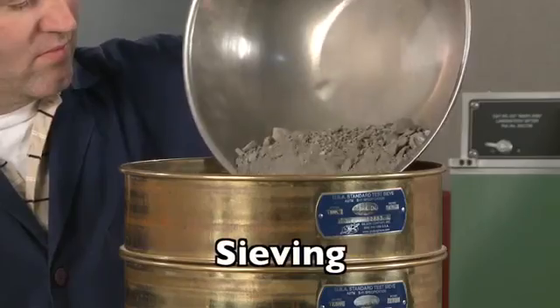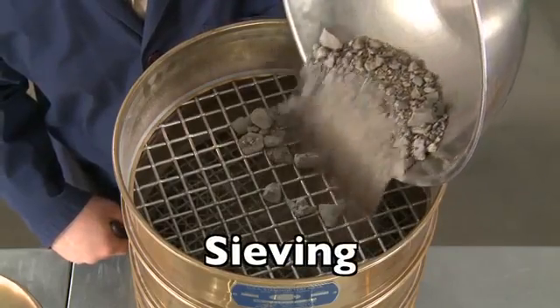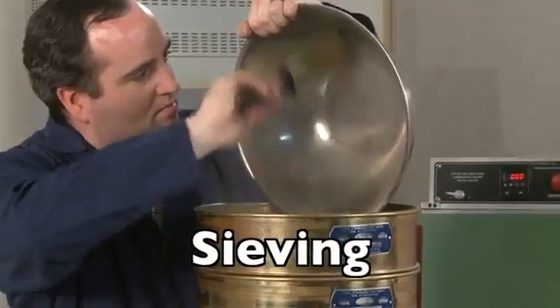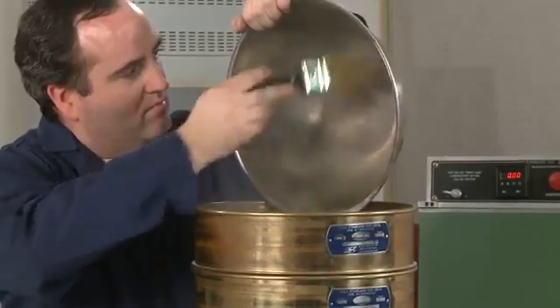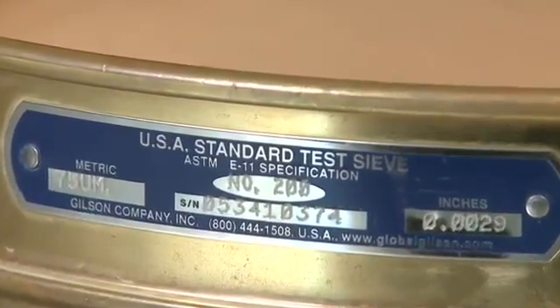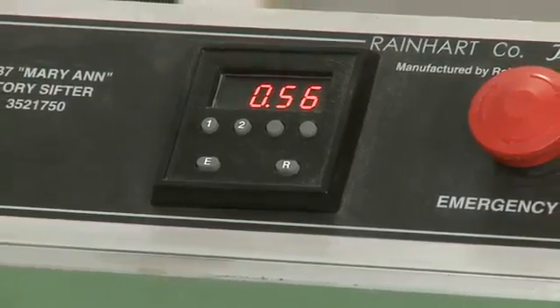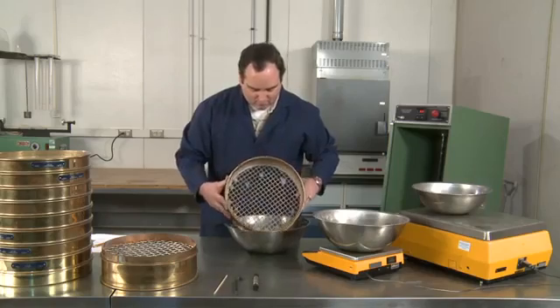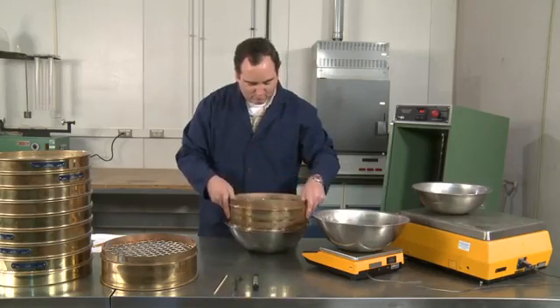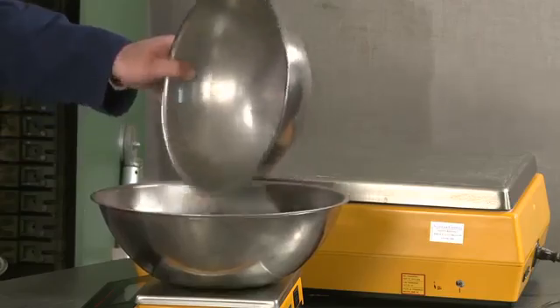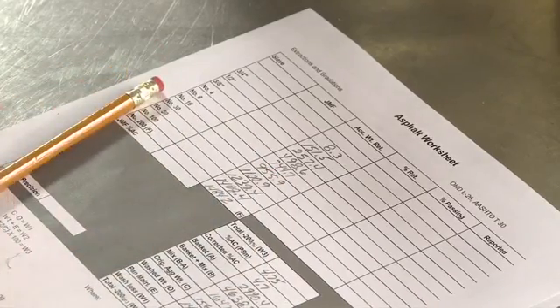To complete the procedure, sieve the dried sample over sieves of various sizes as required by the hot mix asphalt specification, including the number 200. Agitate the sieves by mechanical apparatus for a sufficient period to meet the criterion for adequacy of sieving. According to the applicable specification, record the weights retained on the sieves to the nearest 0.1% of the sample mass.